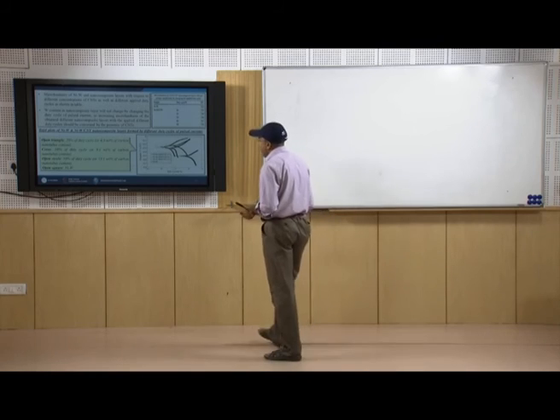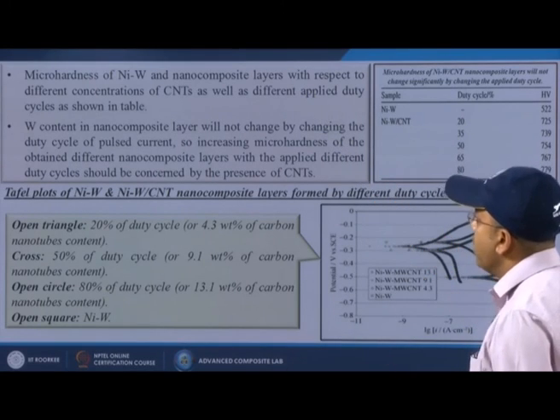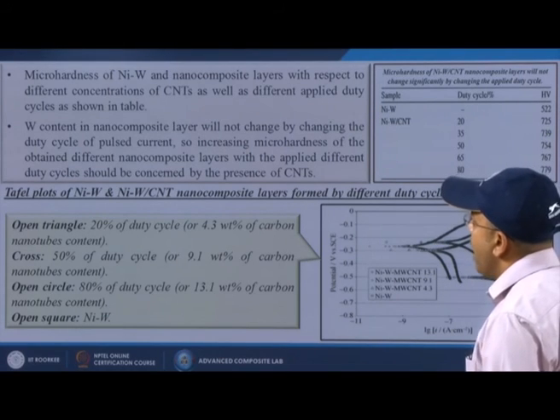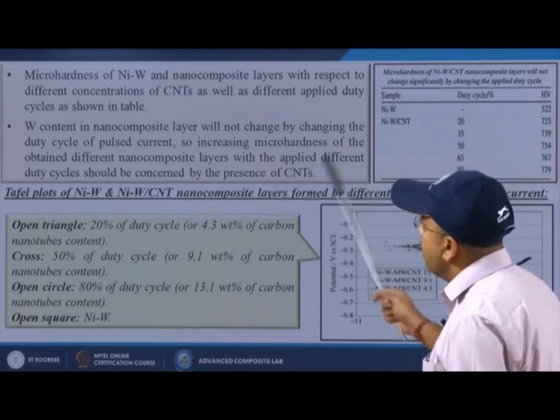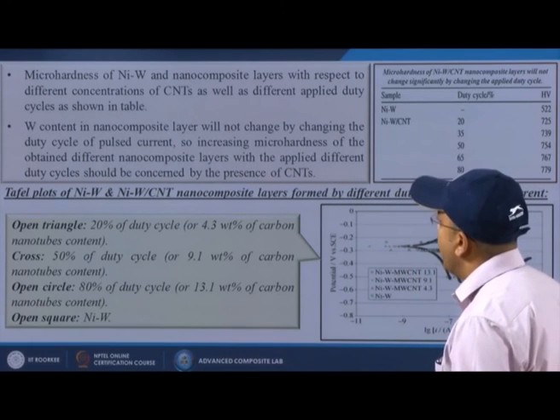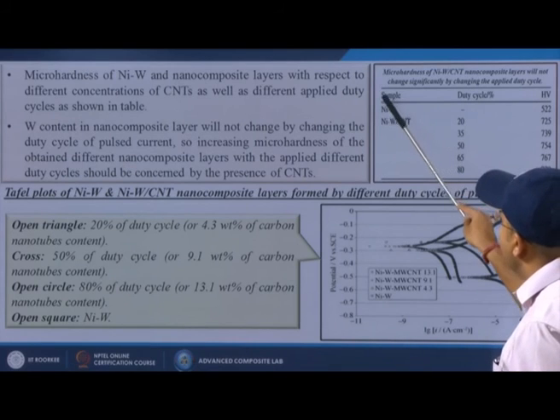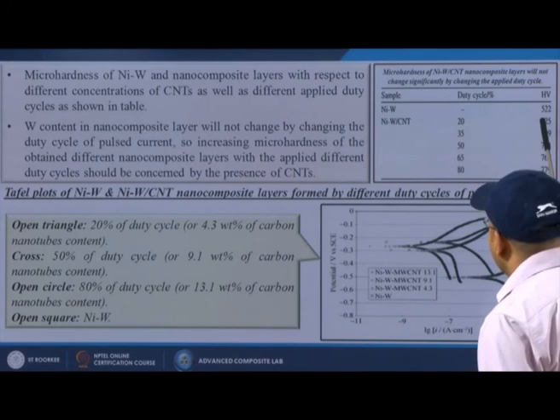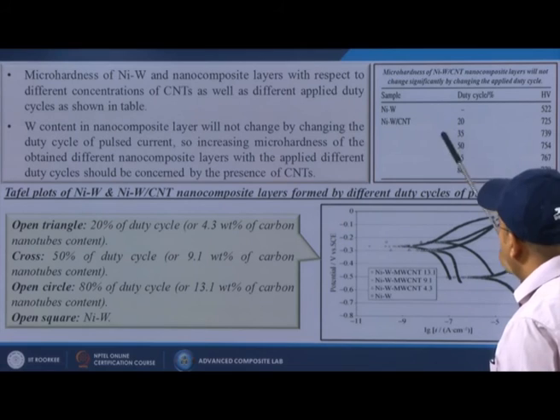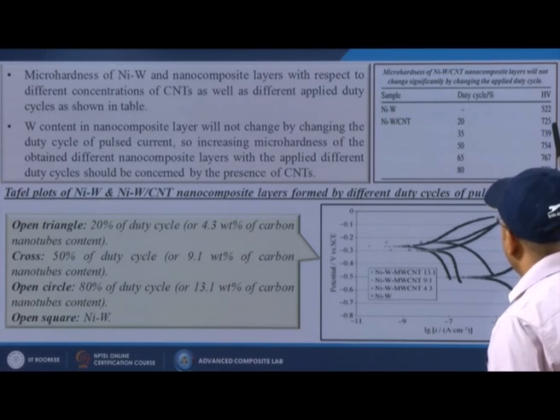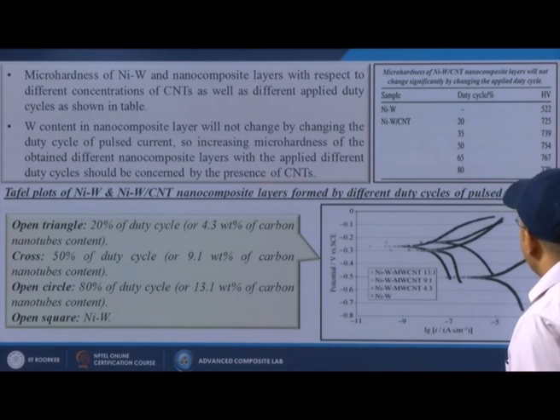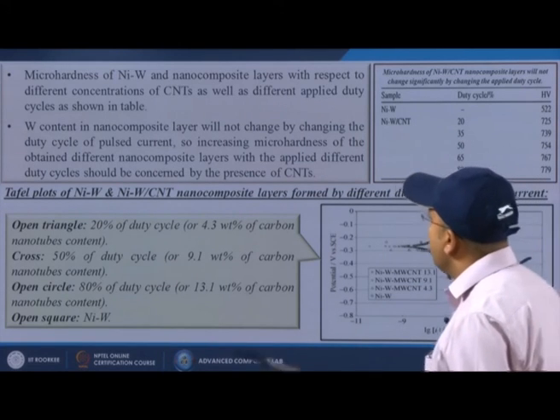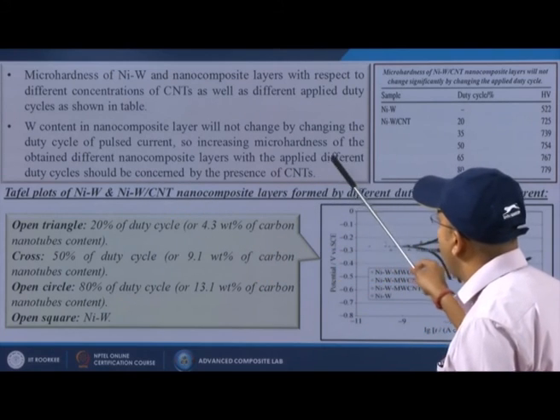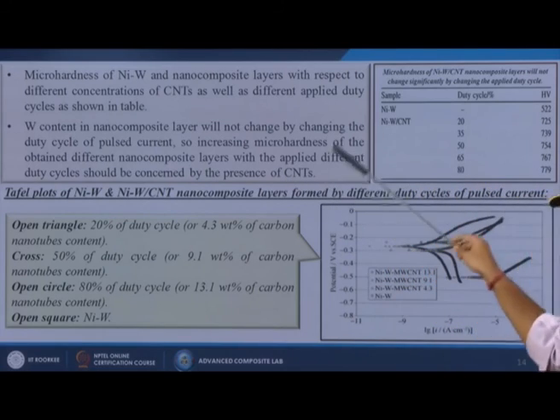Then we have measured the micro hardness also in terms of the duty cycle for these samples. So, micro hardness of nickel tungsten and nanocomposite layers with respect to different concentrations of carbon nanotubes as well as different applied duty cycles is shown in this table. In this case, the tungsten content in the nanocomposite layer will not change by changing the duty cycle of pulsed current. So, when you are only using nickel and tungsten, the hardness value is around 522, but when we introduce the carbon nanotube into the system at the 20% duty cycle, the hardness value goes to around 725, and if we increase the duty cycle up to 80%, the hardness value goes up to 779. So, the increase in micro hardness of the different nanocomposite layers with the applied duty cycles should be attributed to the presence of CNTs. In this case, the carbon nanotube plays a vital role in these systems.